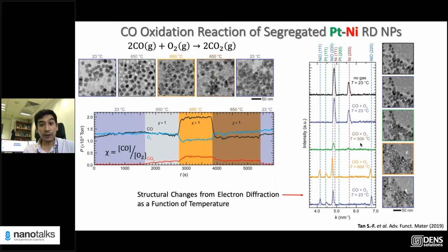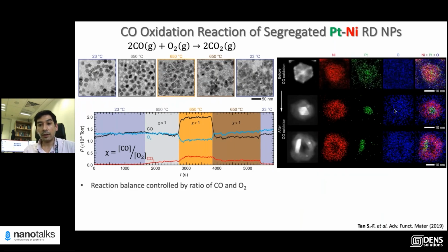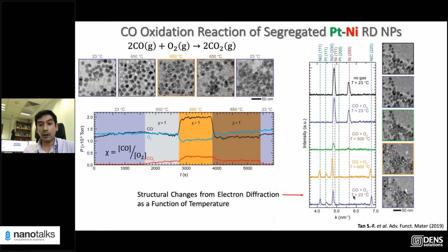You can do in situ diffraction. That's a beauty. You can switch between imaging mode and diffraction mode. So there's a lot of things you can do: calorimetry to monitor the reaction, taking images, and doing diffraction while your reaction is going on. You can unequivocally show that the nickel oxide shell starts forming as the reaction happens. The shell that I showed you earlier has an oxide, but you can also verify through diffraction what type of nickel oxide it is and what's happening to your nanoparticle.